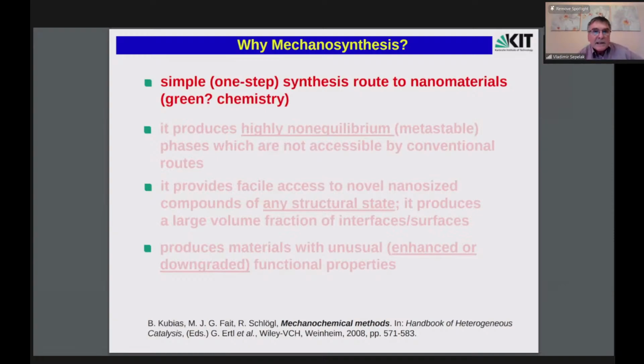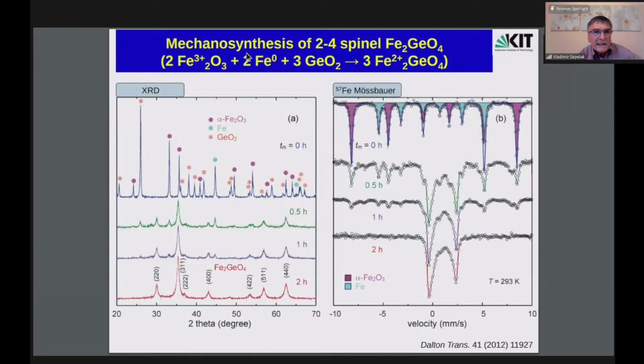Why mechanosynthesis? Why mechanochemical synthesis? There are many points to mention, but I would like to point out only the very relevant ones, which deal with mechanochemical synthesis of complex nano-oxides. It is a very simple one-step route to nanomaterials, and this is clearly visible in the first example, which presents the mechanosynthesis of inverse spinel iron germanate from three various adducts. You have hematite, metallic iron, and germanium oxide, and as you see on the left-hand side, the X-ray diffraction pattern clearly demonstrates that mechanochemical synthesis is completed in 2 hours, and the product is a spinel containing ferrous cations. You can see all the broad lines, which indicate the nanoscale nature of this product.